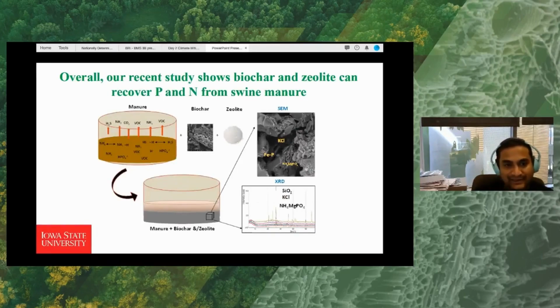So overall, our recent study shows that biochar and zeolite can recover phosphorus and nitrogen from swine manure. In the schematic diagram, we have shown that if we add biochar and zeolite to the manure and then do the scanning electron microscopy and XRD, we find significant association of nitrogen and phosphorus with magnesium, and some iron-phosphorus association without any mineral formation, maybe in the amorphous phase. So nitrogen and phosphorus can be stabilized in the biochar and zeolite system, and we can recover that phosphorus and nitrogen from the system to use as a slow release fertilizer.